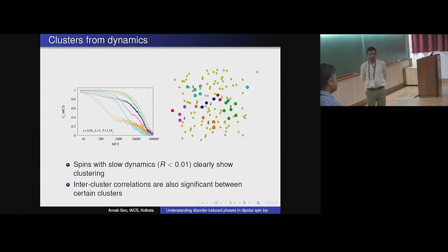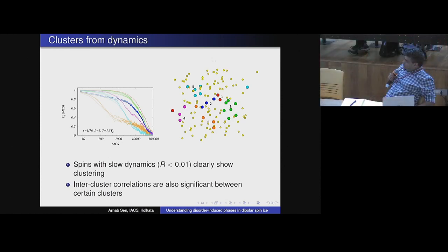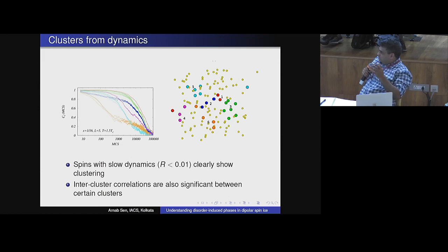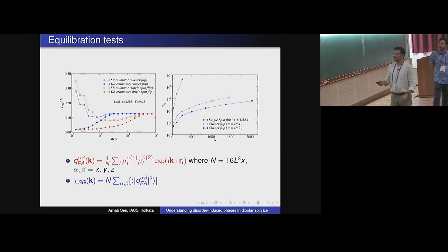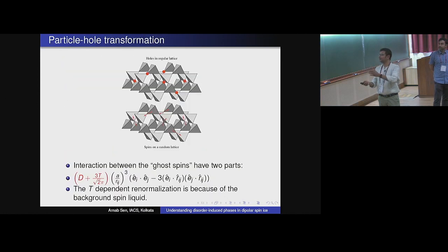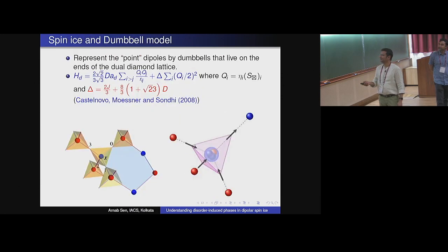This effective charge model you wrote down, I'm wondering, can you do that for any choice of the original parameters of the problem, or did you get lucky? If you remember, the original problem was that there are dipolar interactions and there was some nearest neighbor term. So you can always write down this model formally. But the nice thing is that for these experimental compounds, this delta is reasonably larger than this. That is what allowed you to make the statement that at very low temperature you're still in the ice manifold. Because otherwise, there'll just be some crystallization of the charges and the anti-charges.